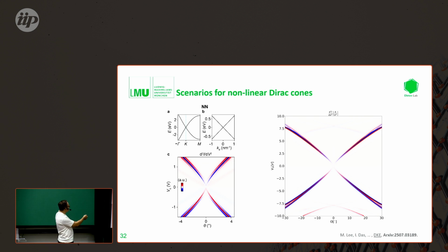For a nearest neighbor tight binding band structure that we can take here, if you go to really high energies, at one point the band structure of course starts to become nonlinear. So that's assumed here. For example, the first nonlinearity that you see here is at the M points, at around 2 electron volts in the energy. However, if we look at the calculated tunneling spectra, this 2 electron volts would correspond electrostatically to a sample bias voltage of around 7 volts, which is basically 5 times higher than the nonlinearity that we observe in our measurements. So because it's 5 times higher, we thought we can exclude this.